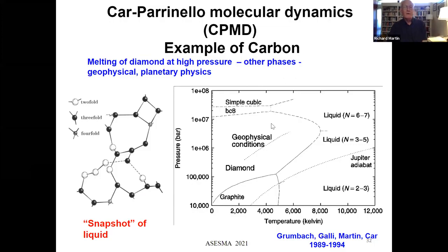This is carbon at very high pressures and temperatures with a prediction of when would diamond melt? What happens under pressure? It was actually controversial at the time. And these are our calculations, and it's turned out that shock waves, including ones done in just the last few years at these giant laser facilities, agreed quite well with the first calculations and somewhat better with more recent calculations. But already the first ones that used the local density approximation really give the basic physics of the problem.